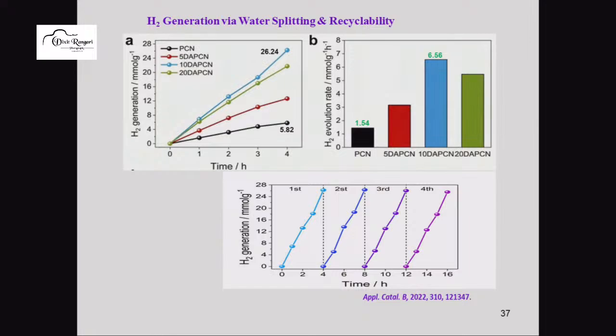In order to generate the green hydrogen, the catalyst was taken. Again, the co-catalyst platinum, from hexachloroplatinic acid, was taken, and it was exposed to visible light. The generated hydrogen was analyzed using GC. And this is the diaminopyridine grafted g-C3N4. It shows a large amount of hydrogen generation compared to the ungrafted g-C3N4.